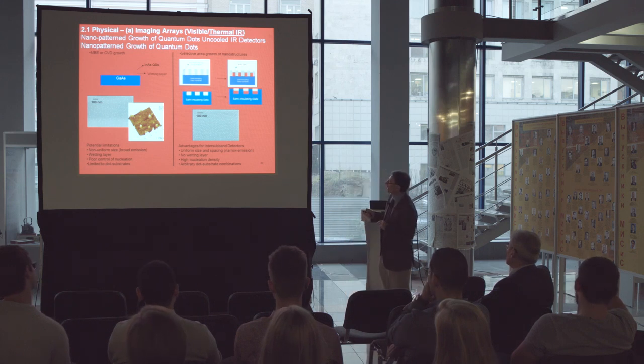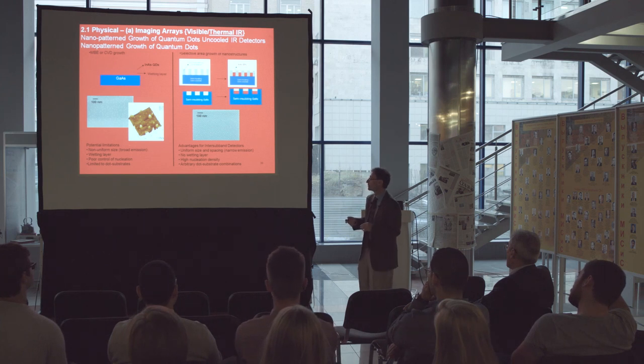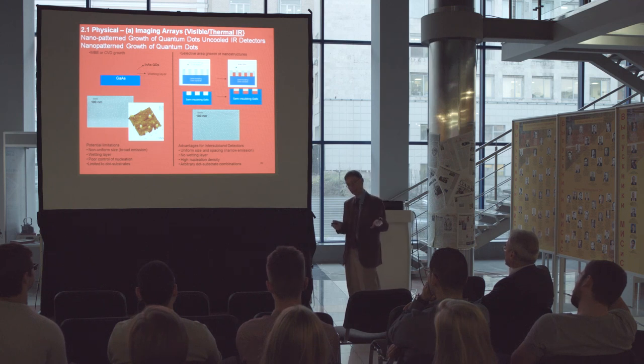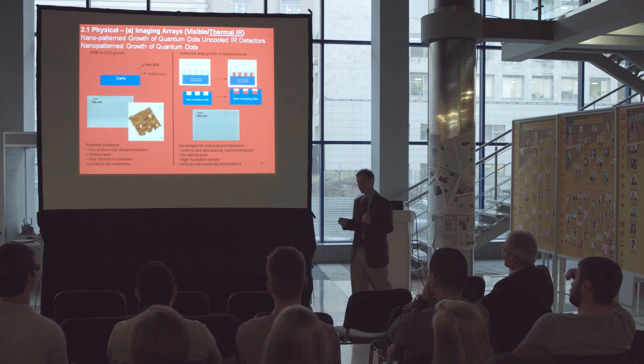So we developed this templating approach. You can get quantum dots this size, but it'll be in a broad distribution of size by traditional techniques. The famous Stranski-Krastanov mode of epitaxy will do that, which is that initially you get a wetting layer, and then the cumulative strain, in the case of indium arsenide on gallium arsenide, is about 7% lattice mismatch. You build up the layer thickness and it breaks down. Growth breaks down from wetting layer to islanding mode.